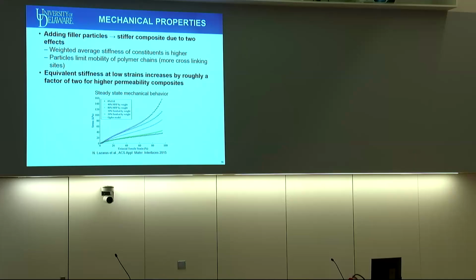Another inevitable trade-off in composite materials is that adding filler particles also results in a stiffer composite, for two main reasons. The first is that the weighted average stiffness of the constituents is simply higher. You have some stiff material in the otherwise soft material. You also get additional effects: the particles limit the mobility of the polymer chains. You have more cross-linking sites. And so we found that for the higher loading fractions in the two materials, the stiffness increased by about a factor of 2 for the higher permeability composites. So we started with a composite with about the same mechanical properties as human skin, and we ended up with a material that had about a factor of 2 higher stiffness. So not ideal from our perspective.